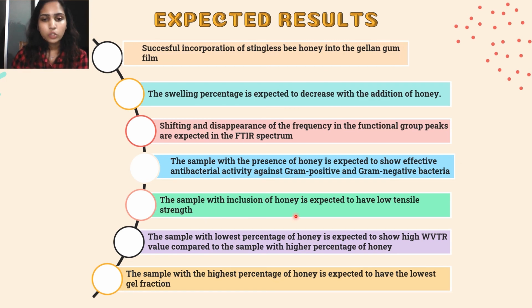The sample with inclusion of honey is expected to have low tensile strength. The sample with the lowest percentage of honey is expected to show high water vapor transmission rate value compared to the sample with higher percentage of honey. And finally, the sample with the highest percentage of honey is expected to have the lowest gel fraction.